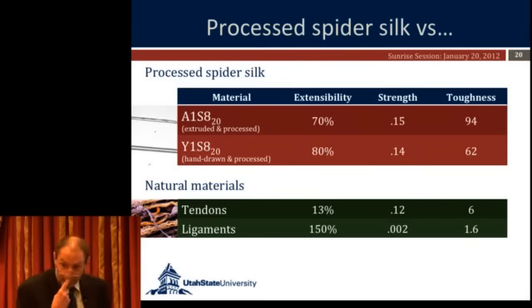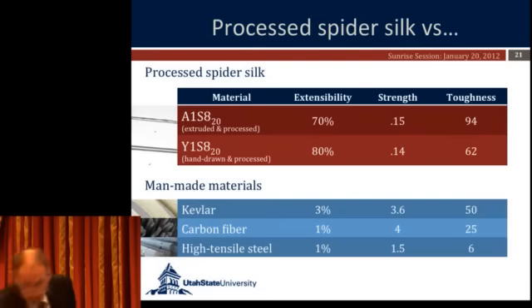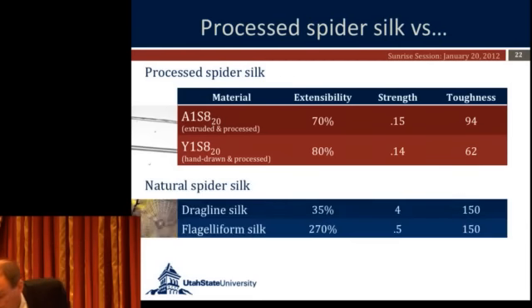Now, if we compare them to some other man-made materials, what you see is that in terms of toughness, we already have materials that are better than Kevlar, carbon fiber, and high tensile steel. What we don't have is quite the strength, so there are applications where we need more strength. But at least on the toughness end, we're ahead of the game. Unfortunately, we're still a long way behind the natural materials. In toughness, we're getting close. Tensile strength, we're still a factor of 5 to a factor of 10 below.